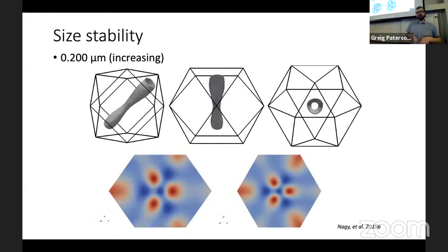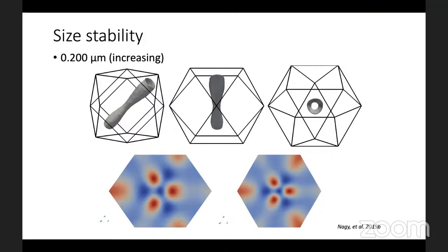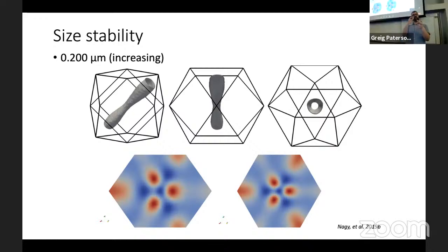And when we do that, the principle is that we take the magnetic structure for one grain, we calculate what the minimum domain structure is, we increase its size a little, and then we keep repeating this process. By doing that, we can understand what's happening to the domain structure within the grain, or the magnetic signal. What's the effect of the grain growing on the magnetic signal?